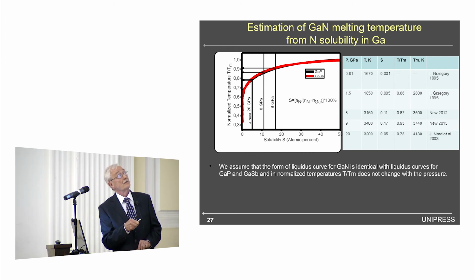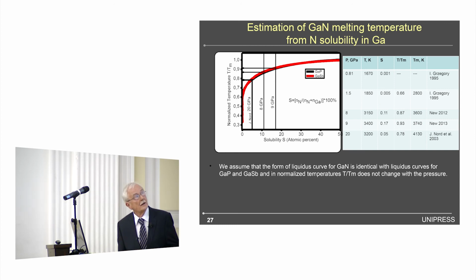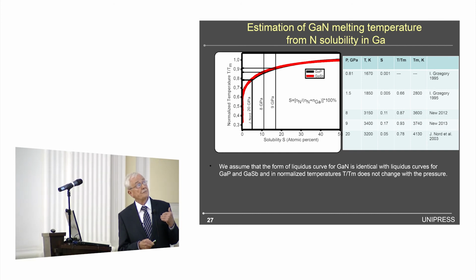This is the liquidus curve. You see these two curves which are here, they are for gallium phosphide and gallium antimonide. So we assume that for gallium nitride, this curve is similar. And from this, if we know the solubility, we can find the corresponding temperature. And these data are shown here, that at 8 kilobars, melting temperature is 3,600, for 9, 3,740.